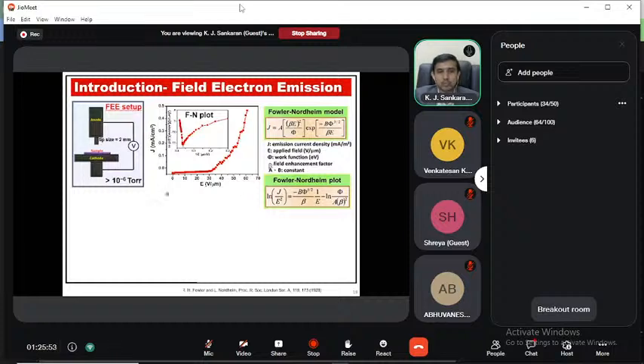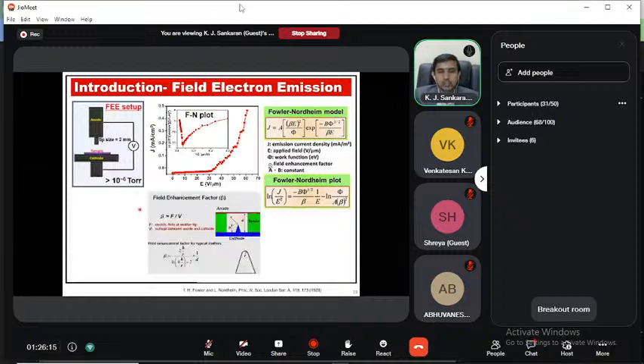So once you apply the field, the current density starts increasing. At one point, there is a sharp increase in the current density, and this point is seen in the FN plot showing the low field and high field segments. The intersection of these two segments gives the turn-on field. From there we can calculate the field enhancement factor. The field enhancement factor plays a key role, especially for nanostructured materials because of their high aspect ratio.